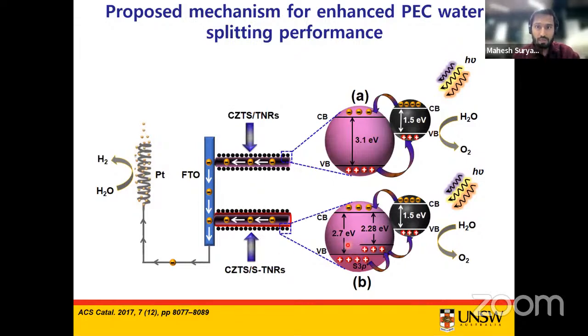When we incorporate the sulfur into TiO2 lattices, as I said, from our DFT calculation there is an upshift of the valence band edge. Here are the TiO2 nanorod arrays without sulfur doping, and here are the TiO2 nanorod arrays with sulfur doping. If you see these two schematics, of course just for schematic purposes, you can see there is an upshift of the valence band edge due to the sulfur doping, which provides an efficient channel or pathway for hole transfer from the TiO2 nanorod arrays to the CZTS nanocrystals or nanoparticles. Whereas in the case of the undoped TiO2 nanorod arrays, there is a huge gap between the valence band edge of these TiO2 nanorods and the CZTS nanoparticles.